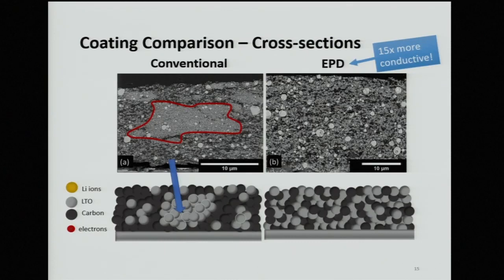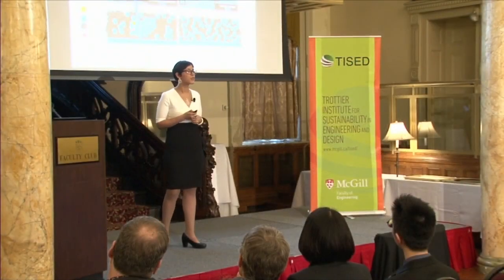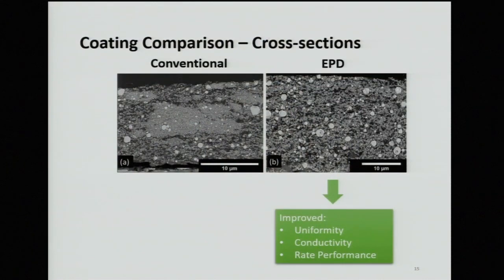Effectively, this is like having a landlocked house that has no access to road. The lithium ions and the electrons can still reach it, but it's a lot slower when it has to flow through the lithium titanate. So we don't have this problem with EPD because we have well-dispersed carbon roads and no landlocked lithium titanate. So now we can say 3 things. EPD produces uniform electrodes. This improves the conductivity of the overall electrode, and this ends with a better performance as a battery.